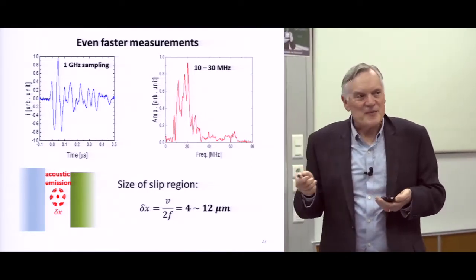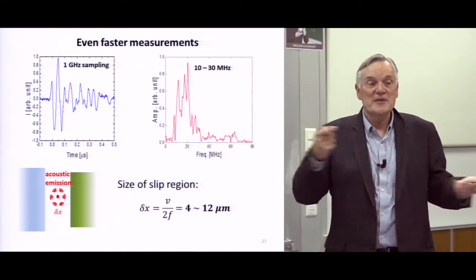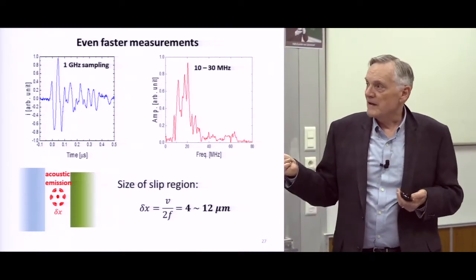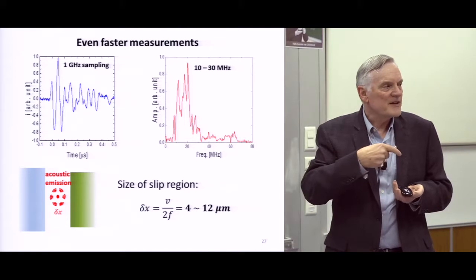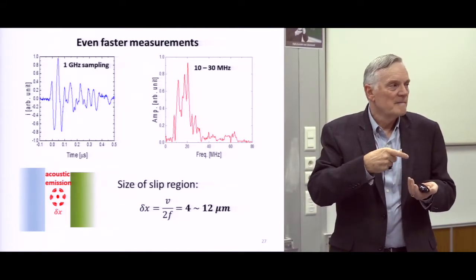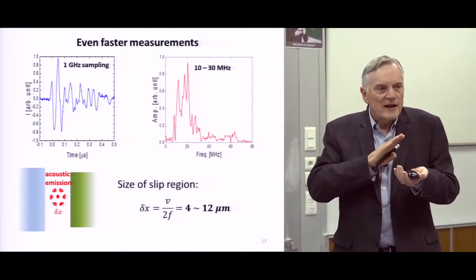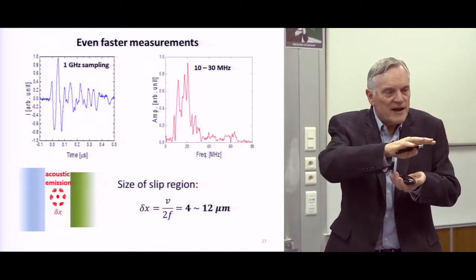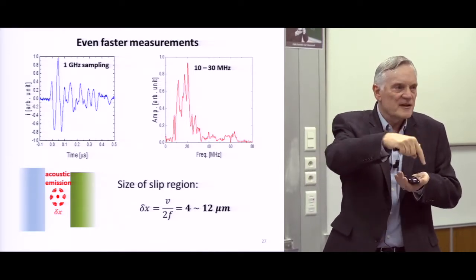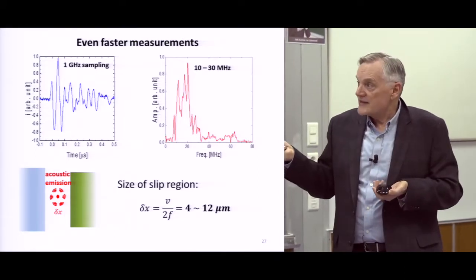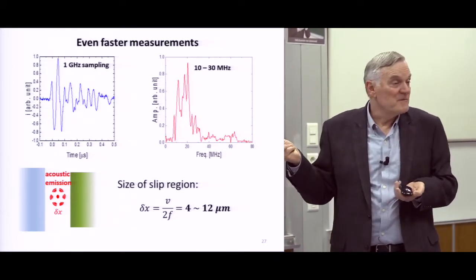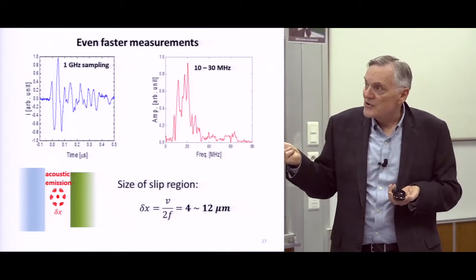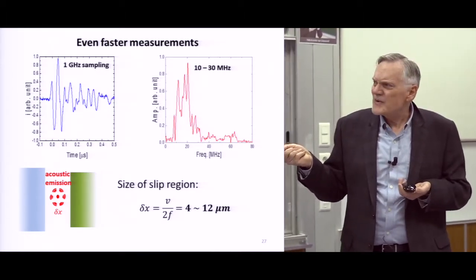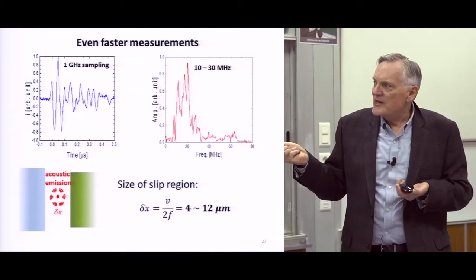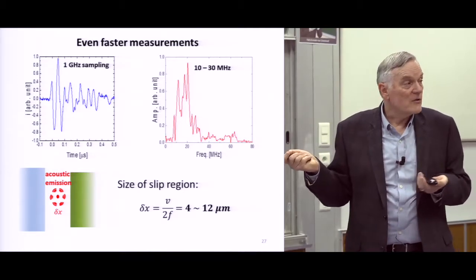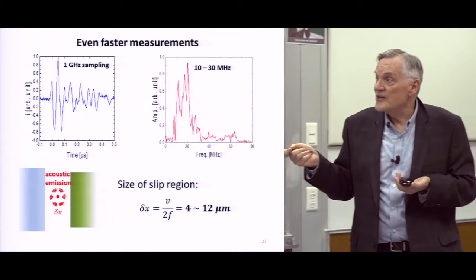And it can't slip over a big area, because otherwise it would be smeared over a much longer time, right? Deformation can't happen faster than the speed of sound in the crystal. If you get a sudden event and it slips an area, that takes a time, the sound velocity times the distance, and that's limited because it can't be more than 100 or maybe even 50 nanoseconds. That tells you that whatever you saw there, and this is really sound, an event happened in a region that might be 5 or less, or 10 or less microns, a very tiny region of your sample.